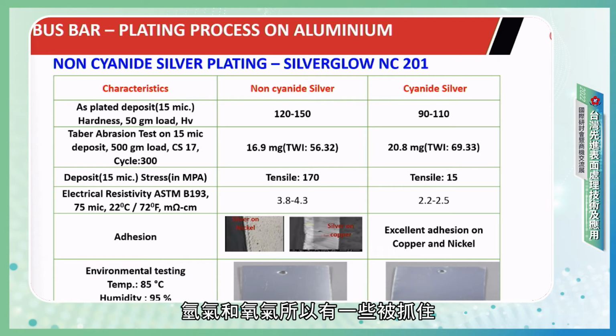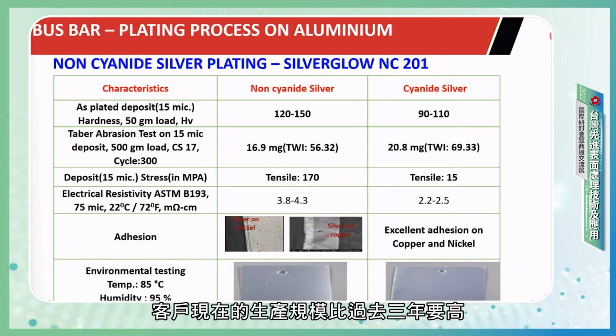So there is some trapping, and those impurities also increase the stress, along with some lattice defects which are also responsible for the higher stress. So comparatively, one negative is that the non-cyanide deposit is a little more brittle. But for our purpose, for example a bus bar with up to 20 or maybe 25 micron of silver, there's absolutely no problem. The customer has been using it in production scale for more than 3 years now.